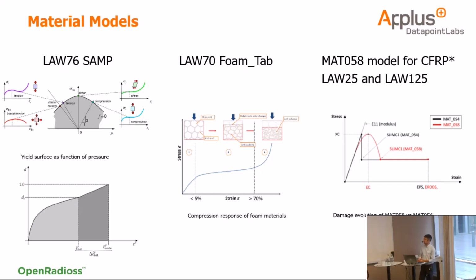So the material model that we are presenting is Law 76, which is called SAMP, that was developed, if I'm not wrong, by Paul Dubois and his team. At the end, it's a multi-yield surface where you need data from different loading conditions to develop this yield surface, which is then used to calculate the proper behavior of the material. Then for foams, there is the foam tabulated model, which is similar to or based on the Fuchang model. And for the composite model, it's Law 25 and Law 125. They are pretty similar to MAT 58 for Dyna.